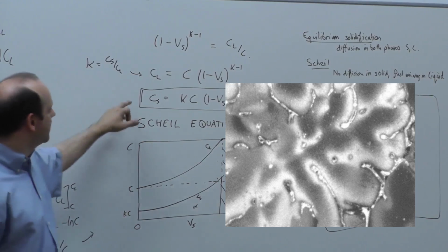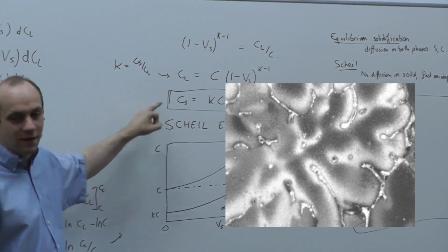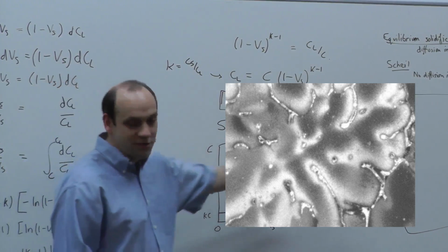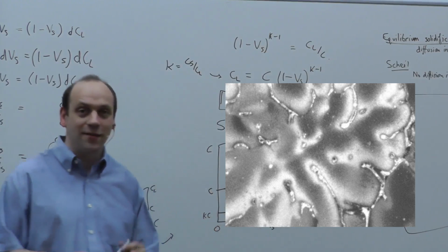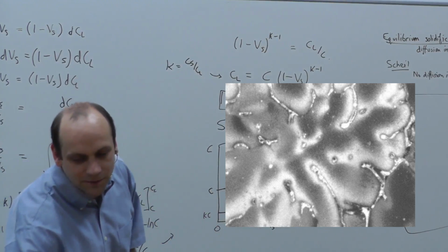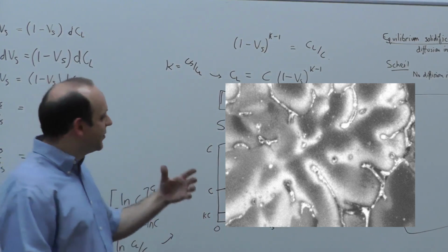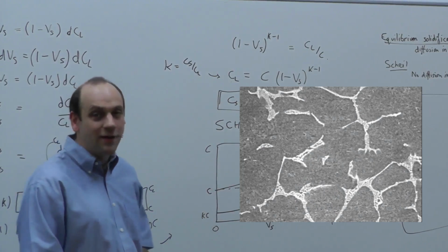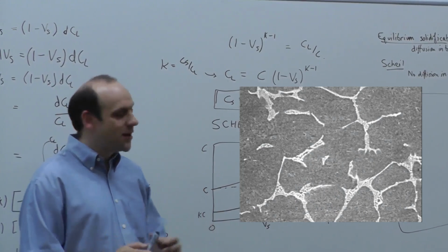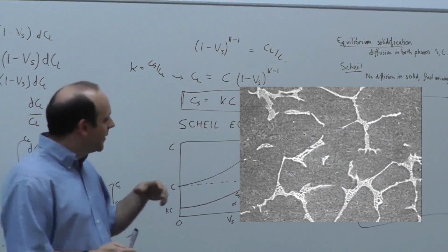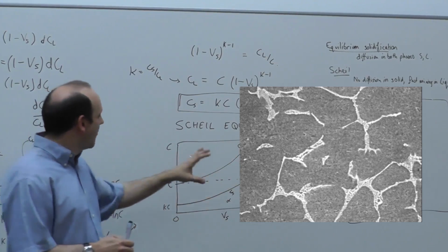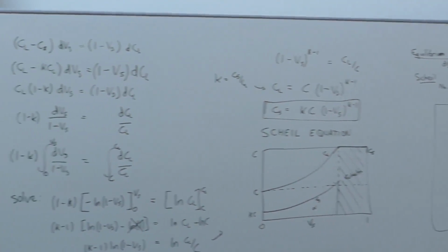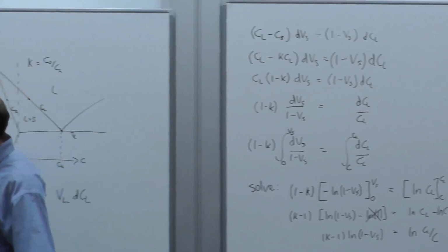So in the Scheil situation, you have solidification where it varies like that, and you can do calculations with that, and you'll get a variation in composition until you get a final eutectic, and that's the message really for this segment. So Scheil always predicts a eutectic, and here's another example here, where you can see the eutectic quite nicely. You can't see the coring as well, but there's another example there, where Scheil always predicts a eutectic, even when at equilibrium solidification, you would come, as in our first case here, into the pure solid phase. Our first case over here.